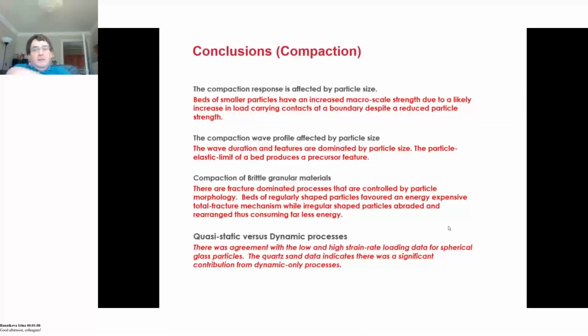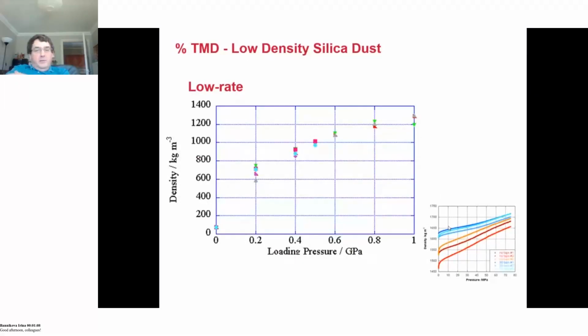Okay. Now, the last thing I just want to mention here is one of the things I was doing at one point was looking at very low density silica dust. This is silica dust, which is round about 5% of the theoretical maximum density. So it's extremely porous. This is the kind of glass spheres, basically empty glass spheres is the best way to describe them. Very dusty, very low particle size. And here we show the low rate compaction, where you're starting at very low density and up it goes to round about 1400 or so kilograms per meter cubed.